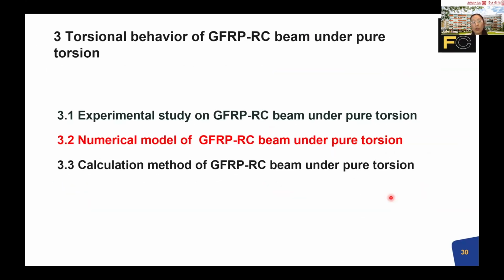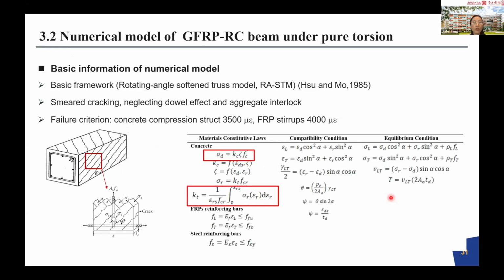Then after the test, we developed a numerical model, which is based on the rotation angle softened truss model, first developed by Hsu and Mo, with similar assumptions to those used in steel RC beams. Here we involve a failure criterion for two failure modes: one is concrete crushing and the other is FRP stirrup rupture. Right now, the FRP stirrup rupture strain is only taken as the average value from the test results.